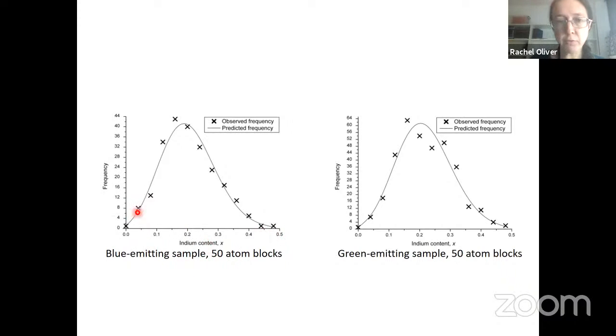Now, the crosses are our actual data, here for a blue emitting sample, a blue quantum well, and here for a green emitting sample. And the line is what we'd expect if the indium content of the quantum well is randomly distributed. So this is what we expect for the single phase case where there's no tendency to form blobs of indium, clusters of high indium content.